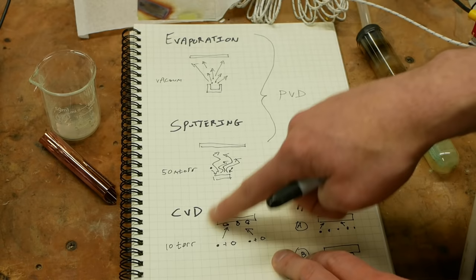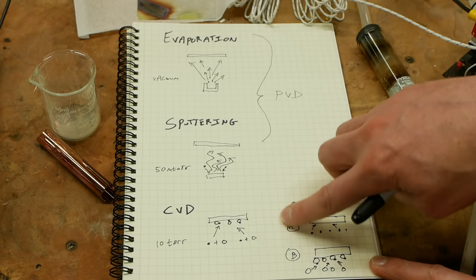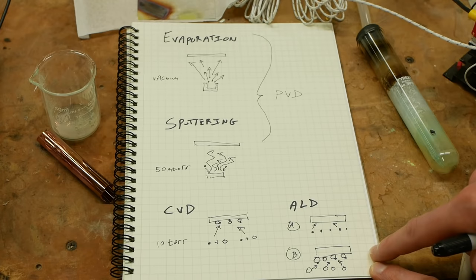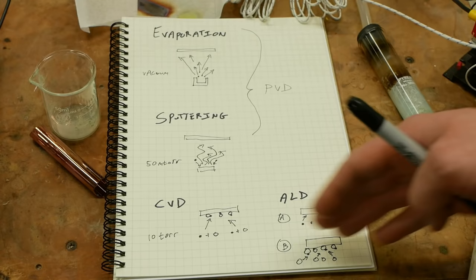And that's where ALD comes in. In this process, we start with just one precursor and it coats the entire object. And we can take our time. Like we can spend a few seconds coating the substrate with precursor A, component A. Then we pump all that out of the chamber. And then we add component B, which reacts with all of this A component that's stuck to the surface and makes the product that we want. Then we pump all that out and go back to A, which lays down a fresh layer of that. And we do a cycle and cycle.